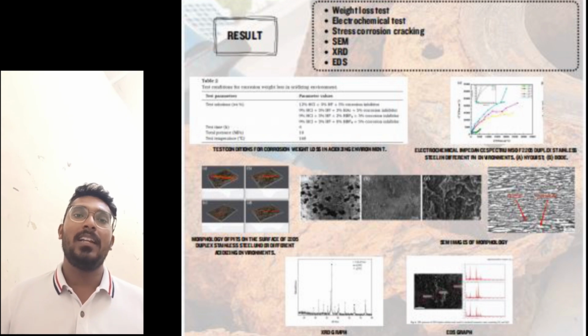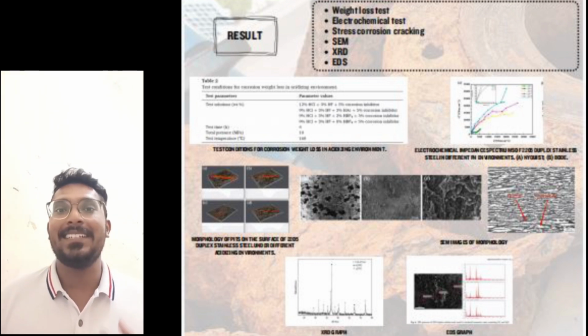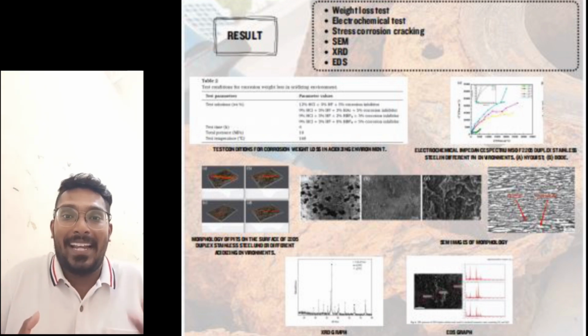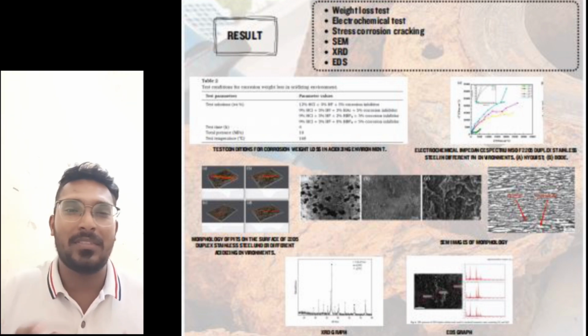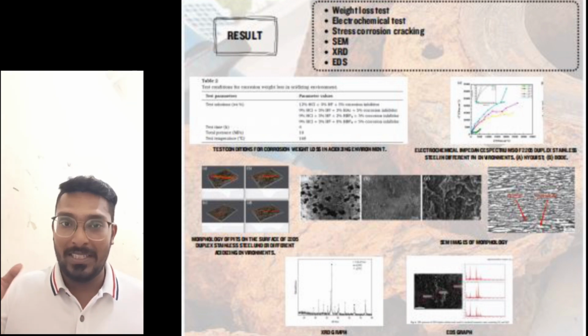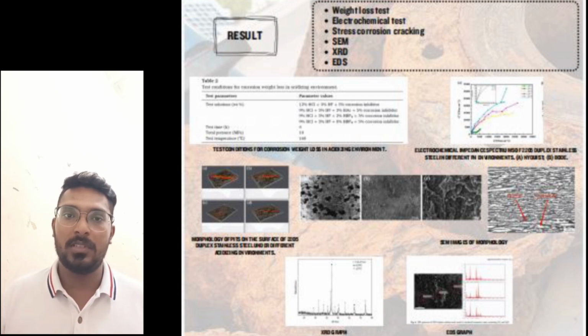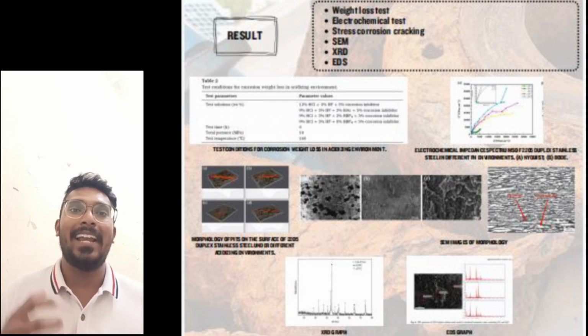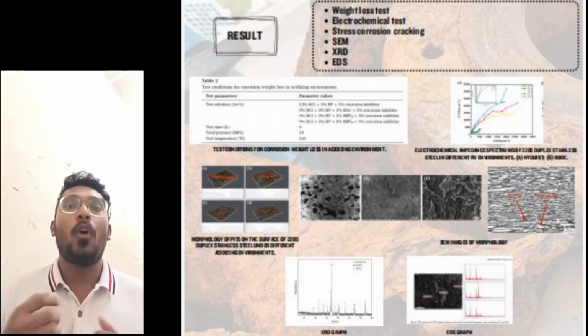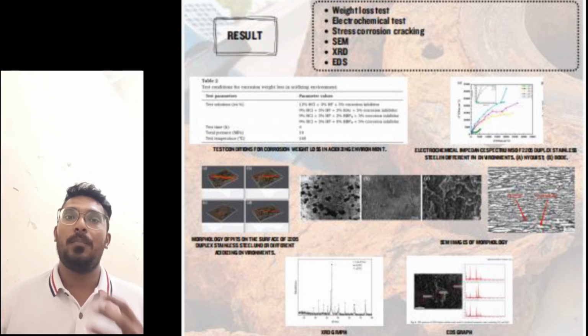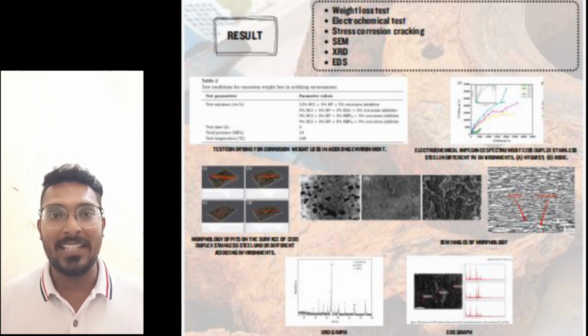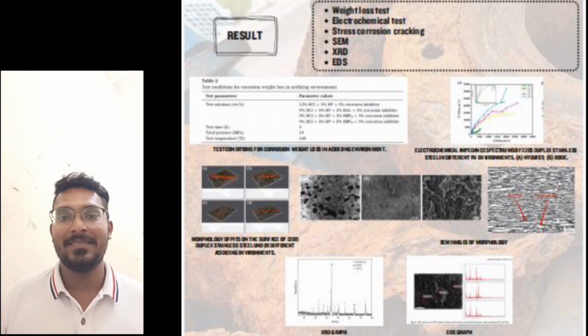And the SCC test on 2205 duplex stainless steel shows no microscopic cracking, but visible corrosion peaks on the surface. We can see in the picture I attached on the poster, the laboratory sectional analysis and high magnification SEM images confirm no cracking. So 2205 duplex stainless steel shows an excellent resistance to stress corrosion cracking in the simulated environment.